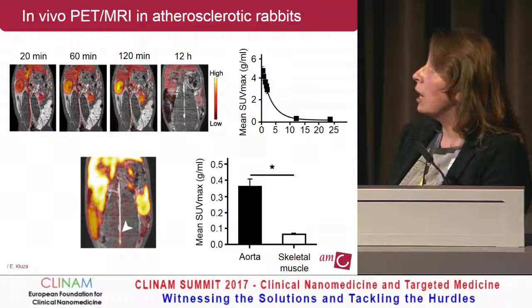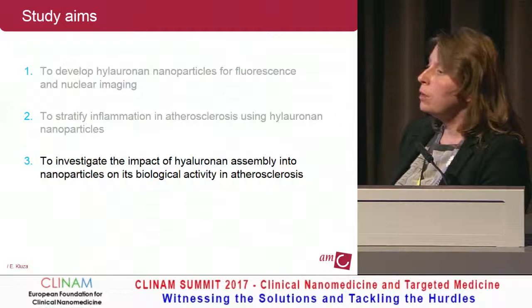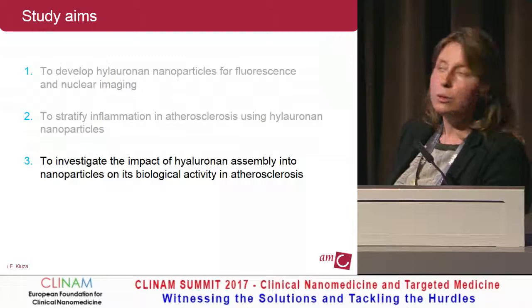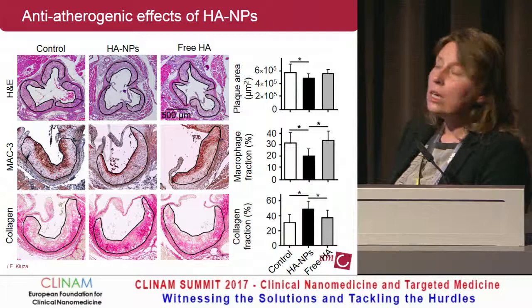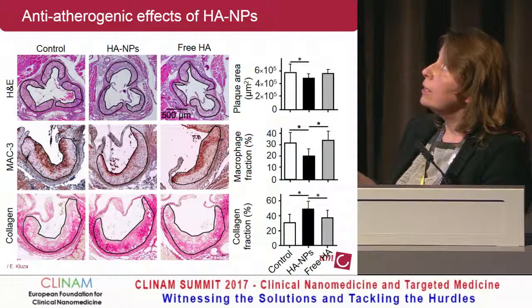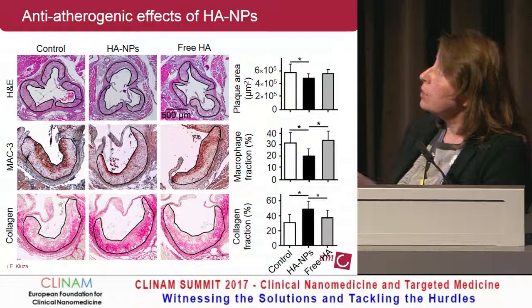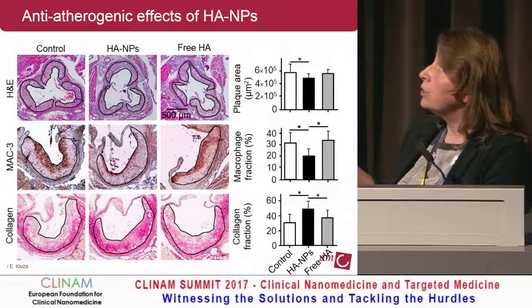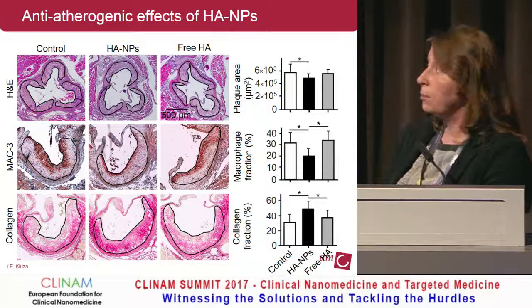The last piece: we were very curious what nanoparticle assembly does to the biological properties of hyaluronan. We performed a therapeutic study in atherosclerosis, treating for 12 weeks, one injection per week, with nanoparticles compared to free hyaluronan. The biggest differences were in the macrophage fraction and collagen fraction — the nanoparticles decreased the macrophage fraction and increased collagen, and these two findings indicate higher plaque stability.